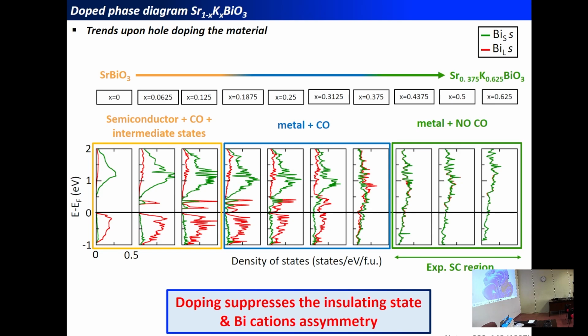How do you know these states are not localized? These states, yeah, this one. So in fact it's metallic, but the electrons are still localized on a preferred bismuth cation. So there is still a charge ordering there. So meaning that there are more electrons on one bismuth cation, not the other one. So there is still an asymmetry of the electronic structure between the two types of bismuth cations, just like we have in the insulating character. One bismuth cation is having more electrons than the other one.